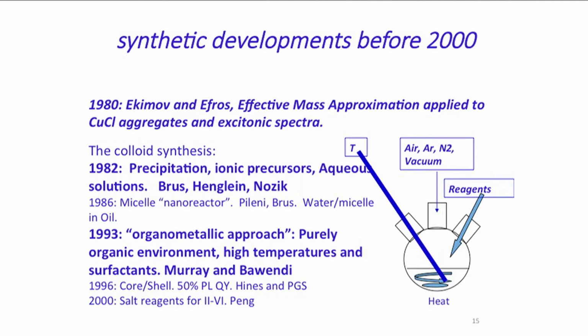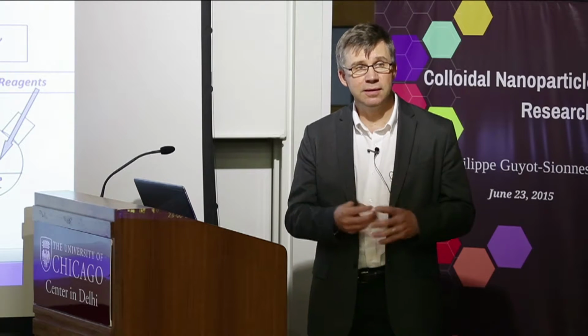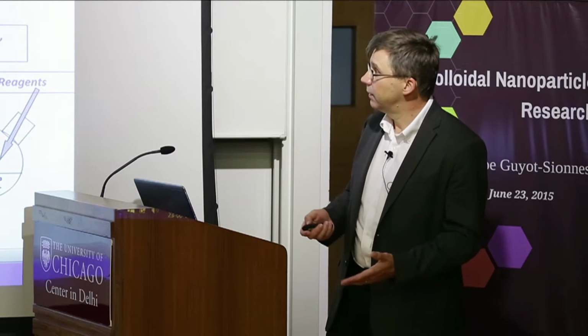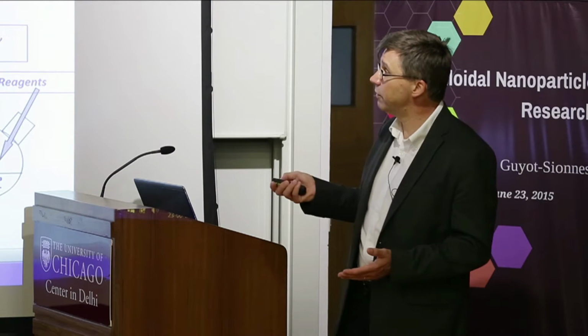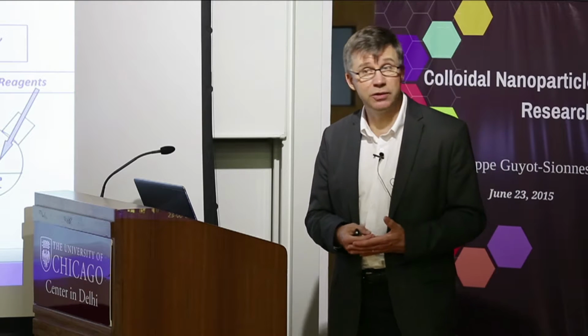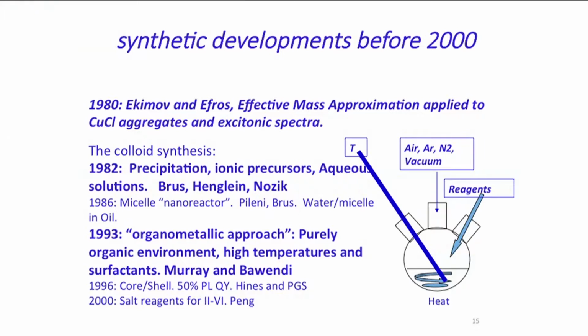In 1980, when this started, it was really mixing salts and glasses together, heating it up, and letting the salt initially dissolve into the glass. And then as it was annealed, eventually this salt would aggregate into nanoparticles inside the glass. And this led to color filters. It took Ekimov and Efros in 1980 to realize that those color filters arose from quantum dots. And they also did an extensive study of copper chloride aggregates. And this saw excitonic spectra shifting with particle size.